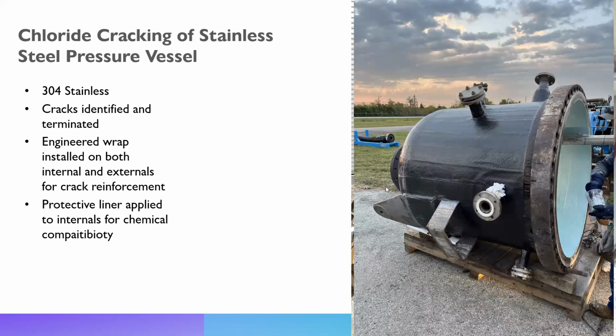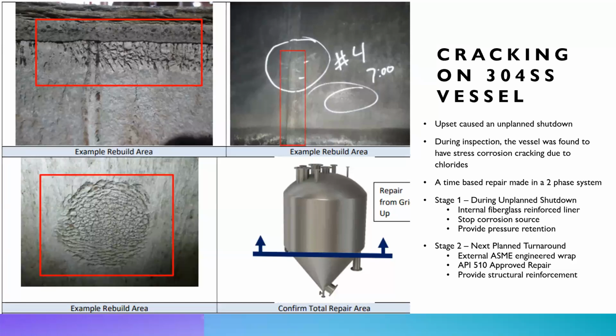So this is typically our go-to for this scenario. If we can get to the inside, we have repaired this from the outside only, but if it is something where we can get it from the inside, then you're protecting your stainless steel from being exposed to the chlorides in the first place. Same scenario here.